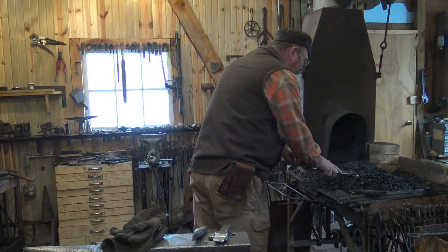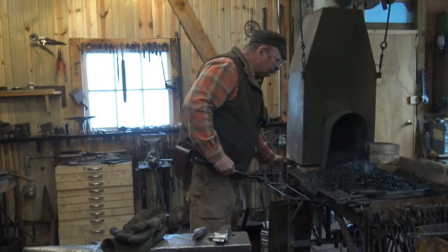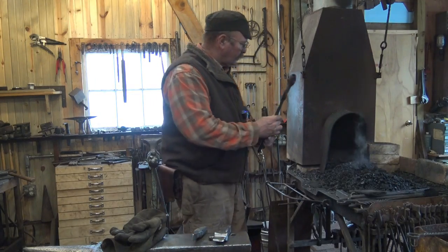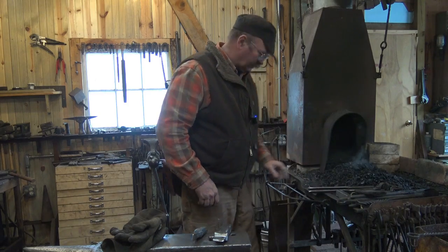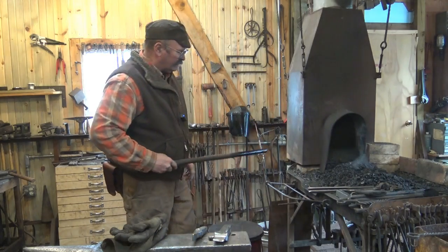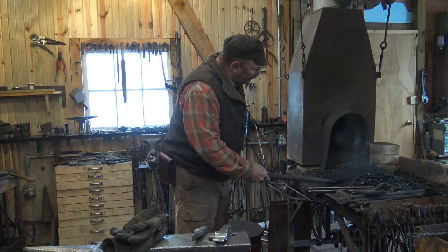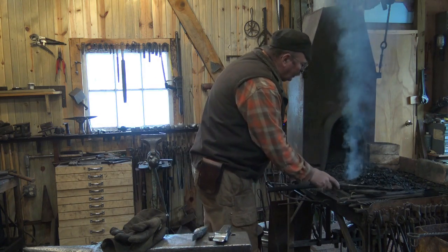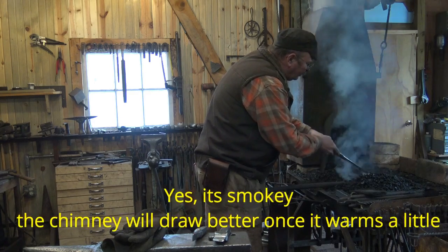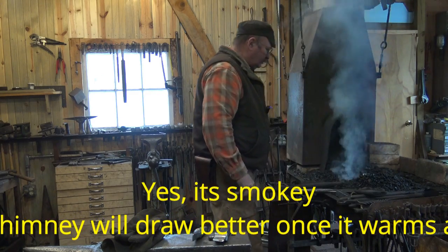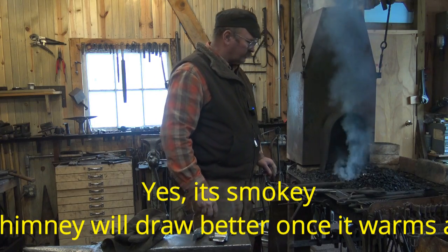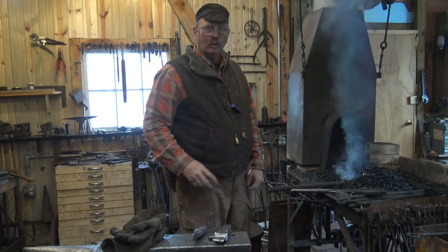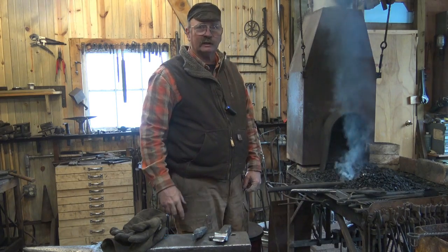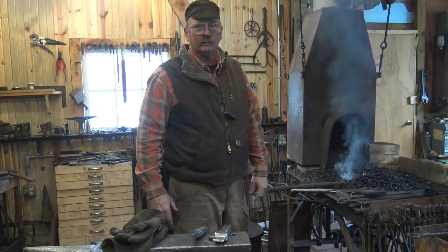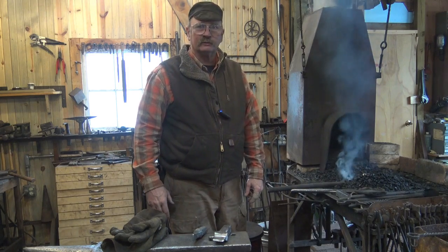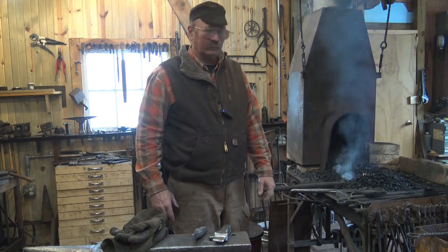So I'm going to put this on the fire, and I'm just going to let it sit there on the top of the fire to kind of preheat a little bit. And while it's doing that, I'm going to heat this bar up down in the fire, and I'll use that bar to preheat my water and my oil, because you don't want to quench in really cold quench medium. Your oil should be 200-300 degrees. Water should be warm to the touch when you go to quench. And since it was 20 degrees last night, this stuff needs to be warmed up.